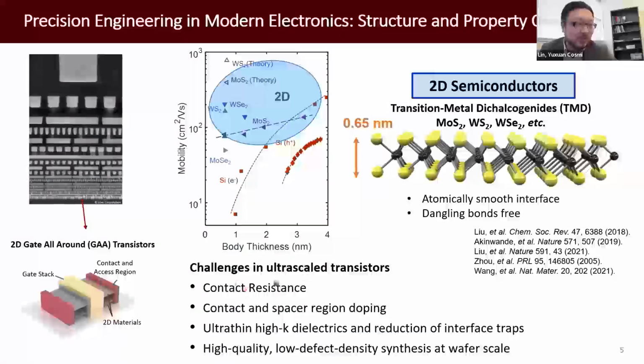For example, how to reduce the contact resistance, how we can design efficient and reliable contact and spacer region doping within the material, and how we can engineer and develop ultra-thin high-K dielectrics as the insulating layer, and engineer the interface to reduce the interface traps. And finally, we also need to develop high-quality, low defect density synthesis of this material at the wafer scale.